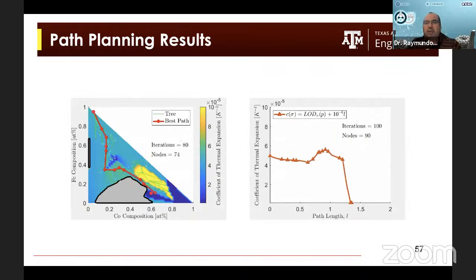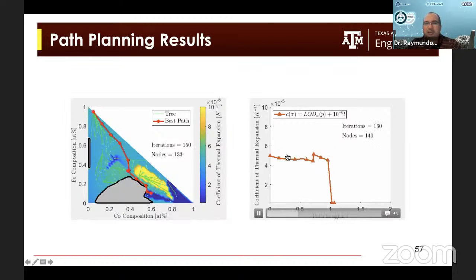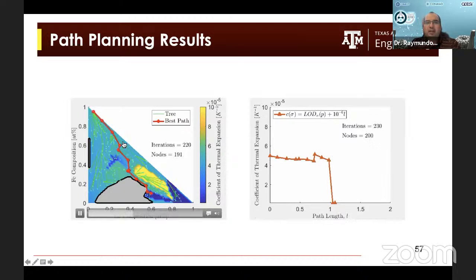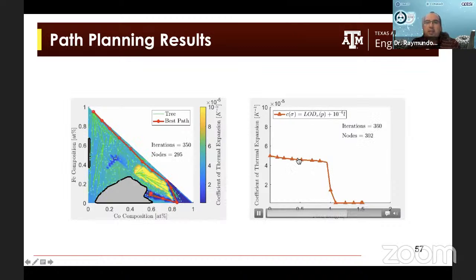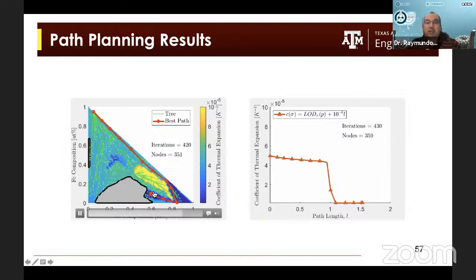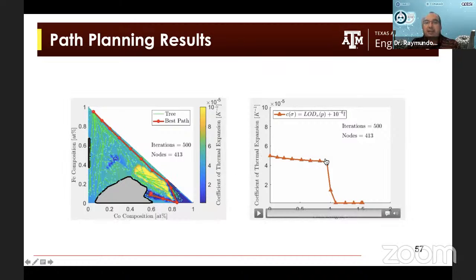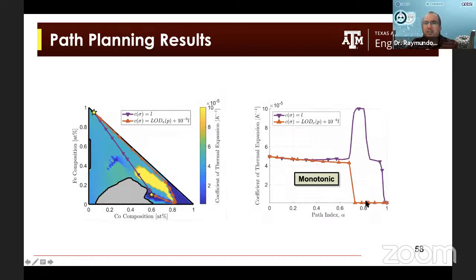This is the algorithm working in real time. Well, not in real time, but you can see how it's working step by step. We are finding a path that avoids obstacles, and at the same time, we are moving in composition to make sure that the thermal expansion coefficient changes monotonically. And you can see that this path is definitely not the shortest path. We actually went away from the sigma phase, and then moved back along this line and connected to this point in order to make sure that the property gradient was monotonic. And this is a dramatic change in behavior between the non-monotonic thermal expansion coefficient profile and the monotonic one.